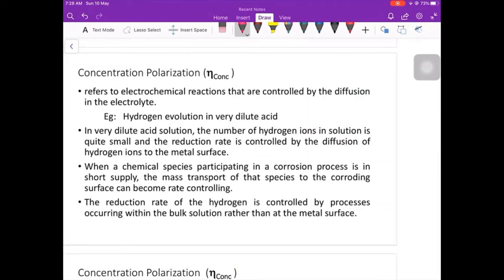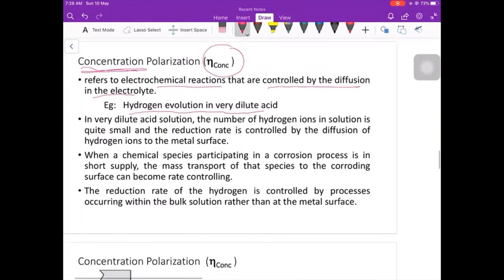Alright, so next, the second type of polarization, where the potential moves from the equilibrium due to concentration. It refers to electrochemical reactions that are controlled by diffusion in the electrolyte. For example, hydrogen evolution in very dilute acid. It just involves the cathodic reaction. There is no concentration polarization for anodic, only the cathodic reaction. In very dilute acid solution, the number of hydrogen ions in solution is very small, and the reaction rate is controlled by the diffusion of hydrogen ions to the metal surface.